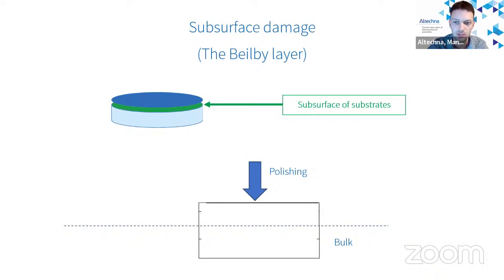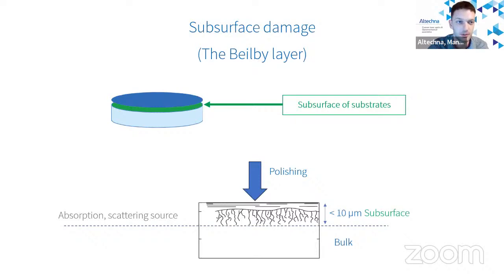This force towards the bulk creates small cracks, which are filled with polishing slurry. Even after repeated cleaning of the substrate, these contaminants remain in the cracks. All these cracks and residual material form the so-called Beilby layer, which acts as an absorption and scattering source, and that leads to a limited damage threshold. Depending on the polishing quality, the thickness of this layer can be up to 10 microns. So it's really relative, depending on the polishing quality.